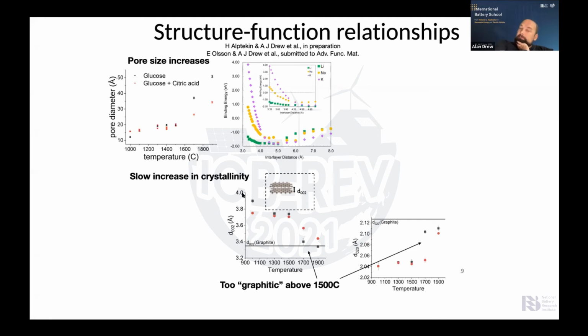We want a lower temperature, D002, in order to get a lower binding energy. We want a lower binding energy because that means we can get the sodium in and out easily. It doesn't get stuck. But when you move to graphite, which is 3, suddenly the binding energy shoots up to a very high level. And even though we might be able to get sodium in, it makes it very hard to get sodium out again.